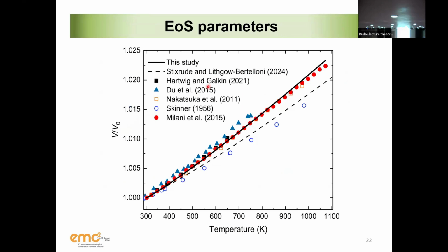The nice thing is that, because we don't have density, we are doing an iterative procedure. When you have so many parameters, you can find a minimum that is completely wrong, so I wanted to check that our minimum actually represented the data. So we calculated the volume expansion at room pressure, where we didn't measure our data. You can see this black line is in excellent agreement, I would say, with modern data of the volume expansion of pyrope. Of course, this one here is calculated with the EOS parameters reported in the compilation of Stixrude and Lithgow-Bertelloni, which is still based on old data of pyrope, as you can notice. So there is a major difference.